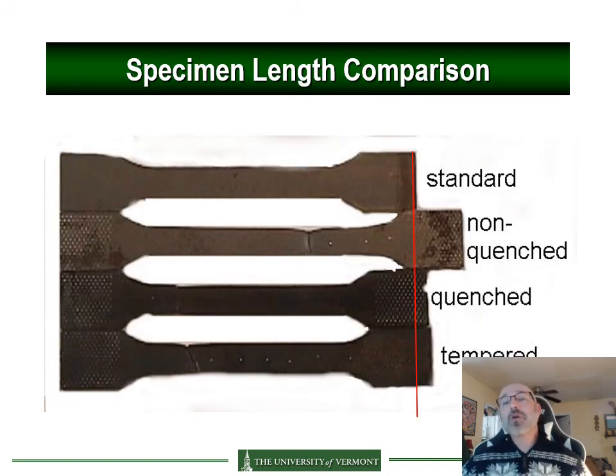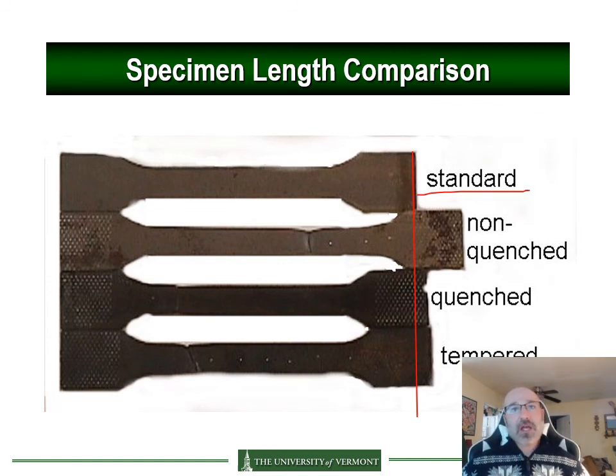So how does this look when we actually compare the specimens for all those? Here's our standard sample right there as our baseline. Now our non-quenched, we can see this was a lot longer if we come off the end here. There's displacement, distortion of this as it stretched before it broke for our non-quenched, whereas our quenched one we have right here, and our tempered one we have right here. So we can see the break style on our quenched, and the break style here with our tempered. Not a huge difference in the overall length, but what we'd come to expect from the previous graph between our quenched and our tempered steel samples.